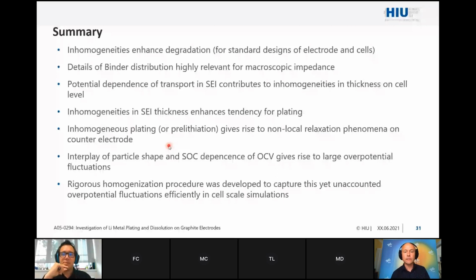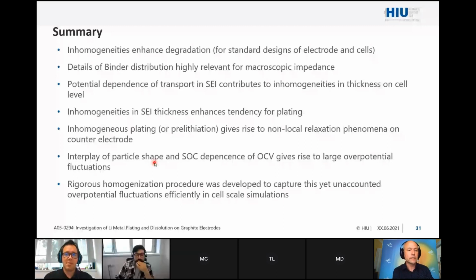And then the interplay of particle shape and SOC dependence on OCV gives rise to large overpotential fluctuation, which makes it necessary, if you want to understand also degradation phenomena with mesoscopic homogenized theories, to do something more, and we try to go in that direction. At least we offer one solution, which of course has to be improved, but which is at least a proposal for a solution. And we did this with a rigorous homogenization procedure. This was developed to capture these yet unaccounted overpotential fluctuations efficiently in cell scale simulation.